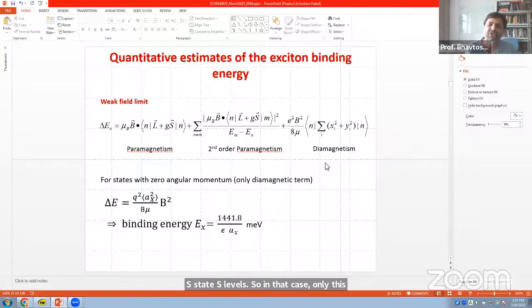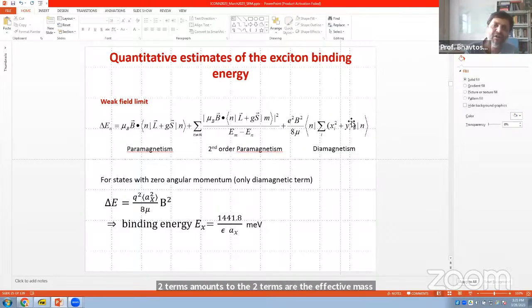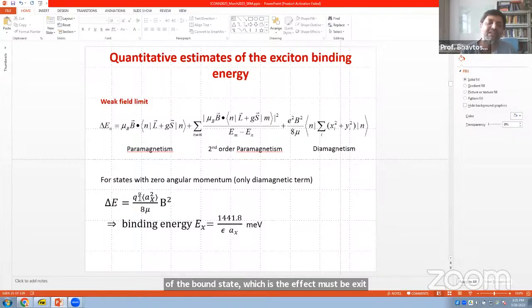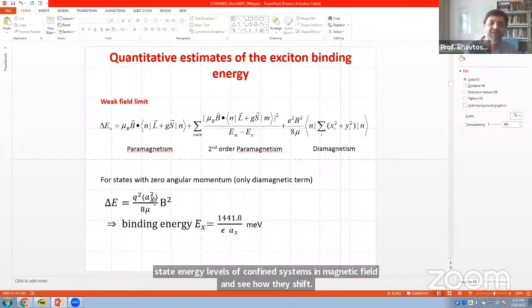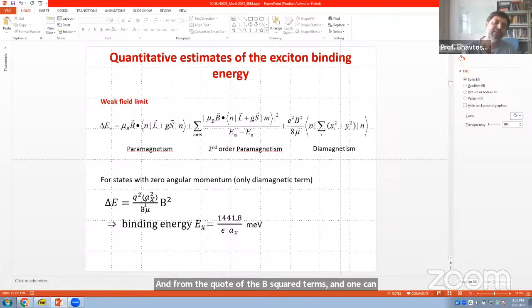And in the weak field limit, the prediction is that the shift of the energy level with magnetic field goes as B squared. The coefficient of this B squared term contains two terms, apart from the fundamental constant, the electronic charge: the effective mass of the bound state, which is the effective mass of the exciton, and the effective radius squared. So quantitatively, one looks at the shift of the ground state energy levels of confined systems in magnetic field and sees how they shift. This is the simplest thing one can do when studying systems in high magnetic field. If one of the two is known, then you can get the other. So that's basically the idea.